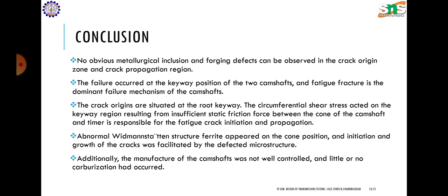Okay, and additionally, the manufacture of the camshaft was not well controlled, and little or no carburization had occurred. So the heat treatment was not done properly, so that the fracture occurred. So from this, I summarize that the main reasons for failure are: one is that there was no proper heat treatment.